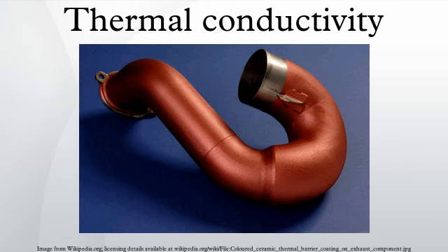Lattice waves. Heat transport in both amorphous and crystalline dielectric solids is by way of elastic vibrations of the lattice. This transport mode is limited by the elastic scattering of acoustic phonons at lattice defects. These predictions were confirmed by the experiments of Chang and Jones on commercial glasses and glass ceramics, where the mean free paths were limited by internal boundary scattering to length scales of 10^-2 cm to 10^-3 cm.